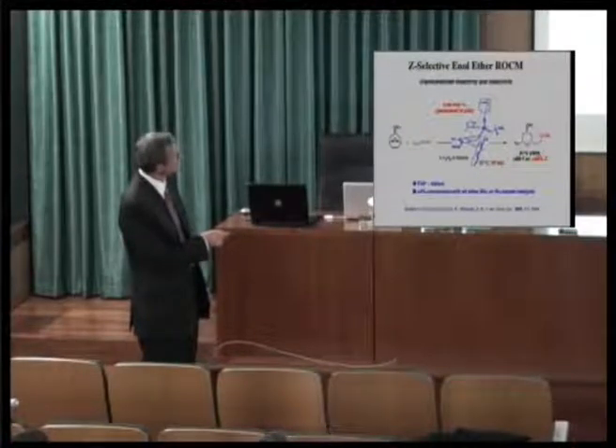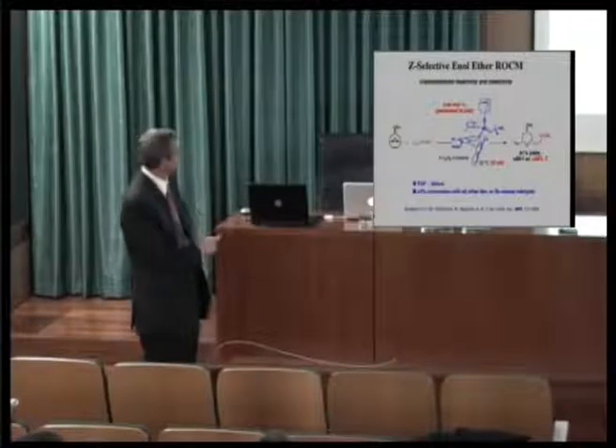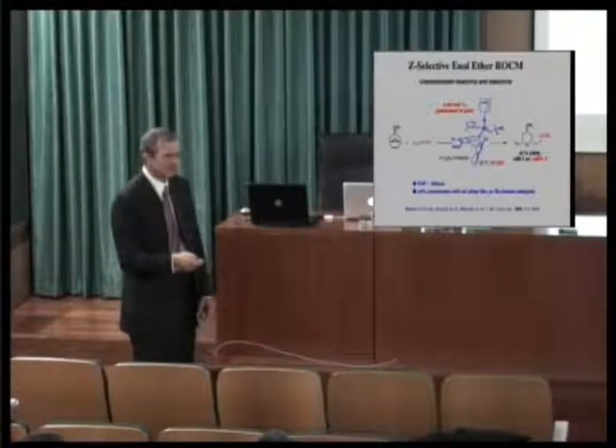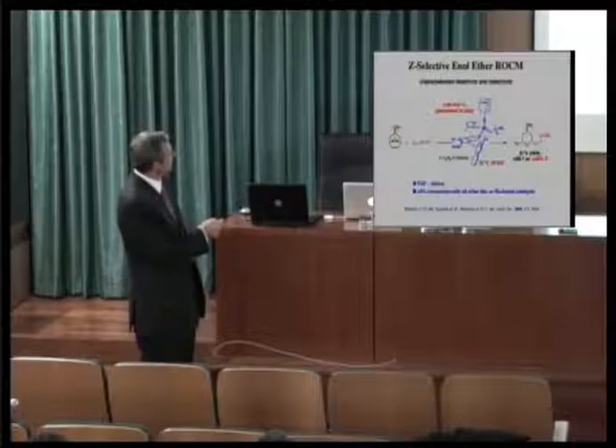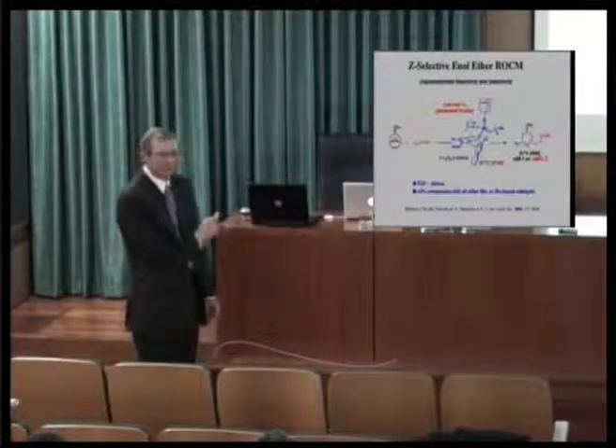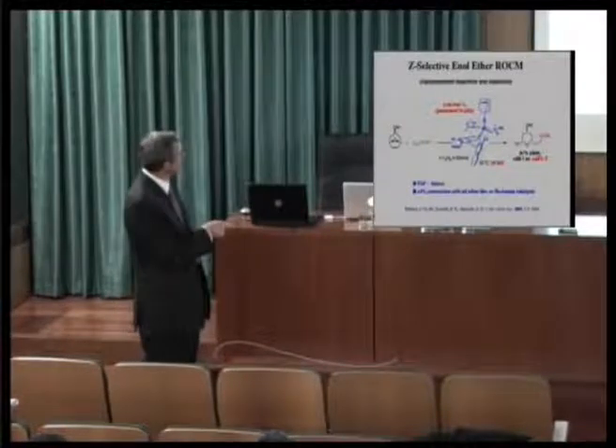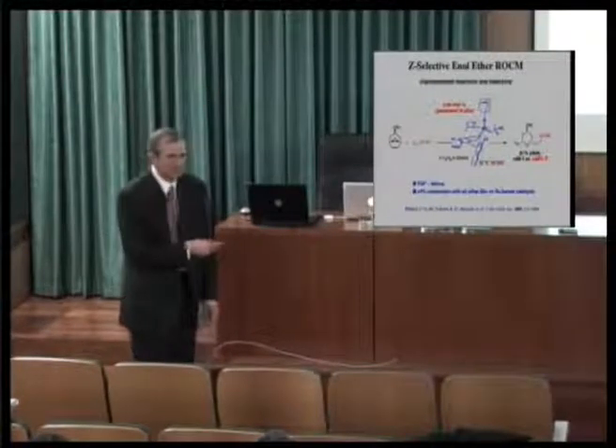So enantioselective and cis only, greater than 98%. This is a very fast reaction. You can use less than 0.1 mole% of the catalyst, and the reaction's over in 30 seconds. So it's a turnover frequency of about 60 per second.